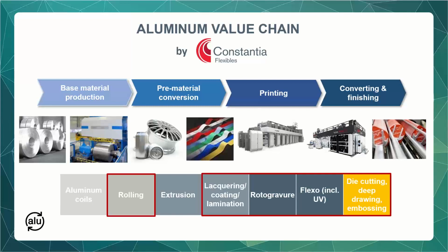The rolling, which is done in several passes on the mills, is then normally followed by a defined heat treatment, which is done to adjust the mechanical properties of the foil according to the needs of the packaging. Then the pre-material conversion provides additional functionalities like sealability or corrosion resistance, tear or puncture resistance. The pre-material conversion technologies used are lacquering, extrusion coating, or different kinds of lamination technologies.